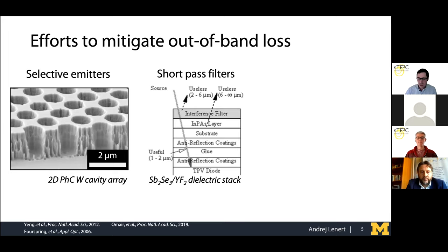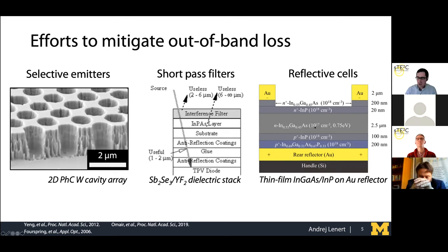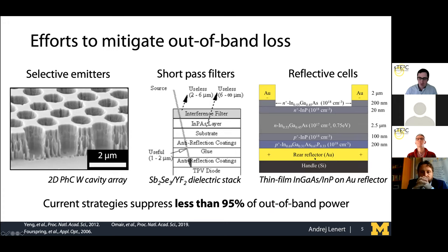And I just want to show some of the previous efforts that have been done in mitigating out-of-band radiation. These include selective emitters, including photonic crystal cavities that have modes that only emit above the band gap, multi-layer structures or combination of plasma filters and interference filters. And then more recently, the work that I alluded to by the group out of Berkeley, which looked at a thin film indium gallium arsenide photovoltaic cell on a back with a high back surface reflectance that's enabled by gold BSR. However, one of the limitations of these past approaches has been that they only suppress 95% of the out-of-band power. In particular, this state-of-the-art device achieves 29% efficiency with 95% suppression of out-of-band power.